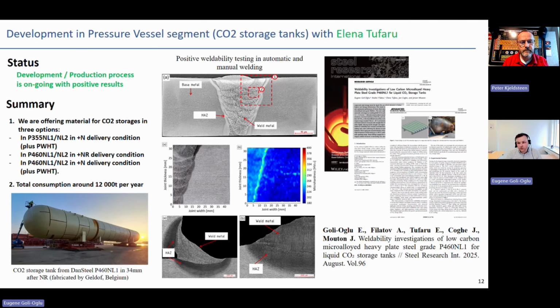The difference between those concepts is that in the case of P355, if you're using the same pressure, wall thickness should be higher. And in the case of P460, due to the higher strength of the material, wall thickness could go down, and this difference is around 25-30%. So from one side, you are investing more into material, but from the other side, you are saving on the wall thickness, and you are saving on the weight of the final construction.